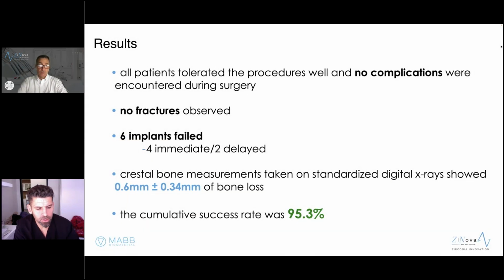The results: all patients tolerated the procedures well, and no complications were encountered during surgery. Very importantly, no fractures were observed. Now, there were 6 implants that had failed, 4 in the immediate group and 2 in the delayed group. This was failure to osseointegrate. And crestal bone measurements taken on the standardized digital x-ray showed a 0.6 millimeter bone loss, with a standard deviation of 0.34 millimeters.